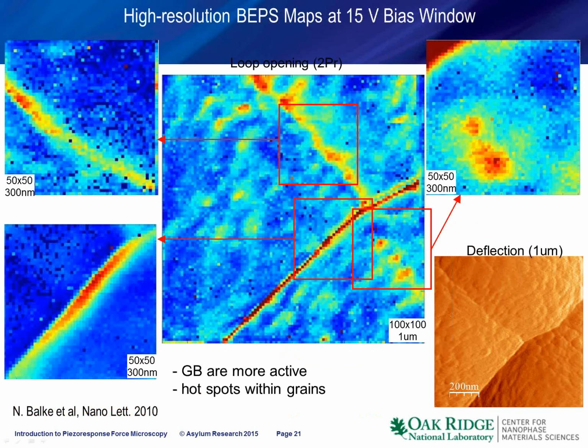And in fact, we can also perform the mapping. This slide illustrates perhaps one of the most beautiful SPM images I've seen. So this is the 1 micron map of the sample surface. The color here is the area under the hysteresis loop. And you can see that the hysteresis loop opens only on the topographic features. So we see a strong loop opening across the grain boundary. We have weaker loop opening across this wavy feature going from the center to the top left corner. And we see a number of hot spots inside the material.